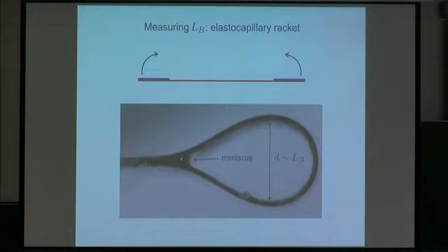And you end up with such a racket. Maybe it's not obvious, but here you have some liquid meniscus. This is blue liquid, and the red racket will be like that. And what you can show easily is that what sets the shape of this racket will be a balance again between surface tension and the bending stiffness of the racket. So you expect the width of the racket, for instance, to be proportional to this bending length. So that's a way to measure this length.